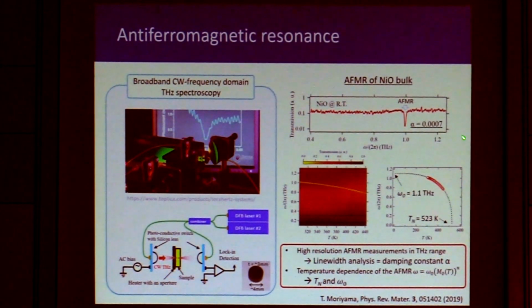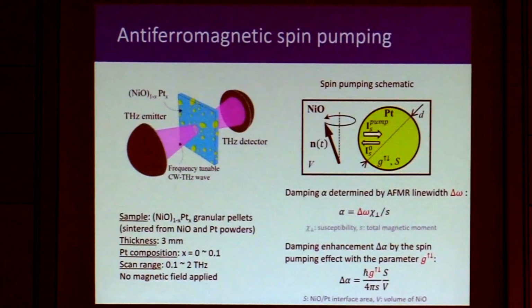And from the linewidth, we can characterize damping to be like 10 to the negative 4th, which is consistent with previous reports. So for this antiferromagnet, there's no point applying a magnetic field. Even if we apply the magnetic field, there is not much change in the resonance frequency. So instead, we just change the sample temperature and then measure this resonance. And from this data, we can extract the intrinsic resonance frequency of the nickel oxide as well as the Néel temperature. Using this setup, we actually did an antiferromagnetic spin pumping experiment.